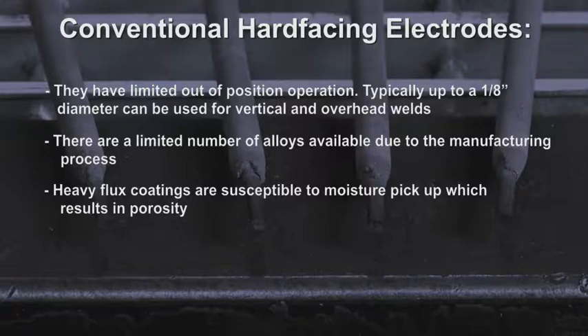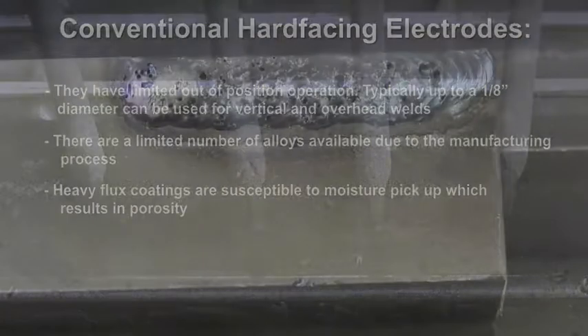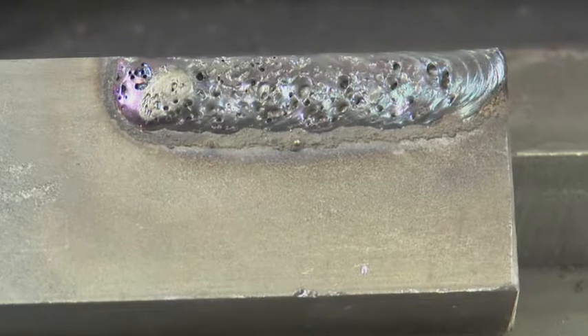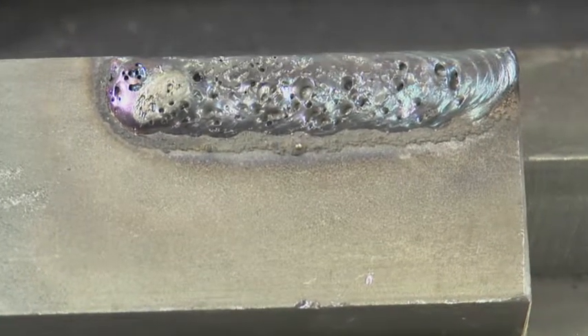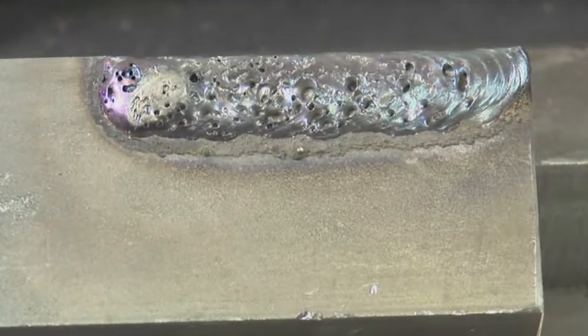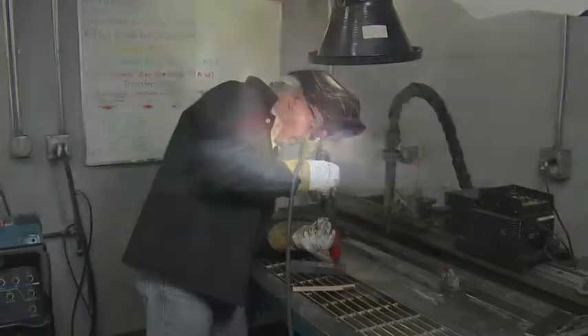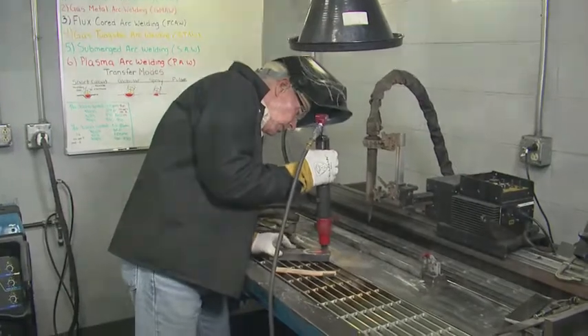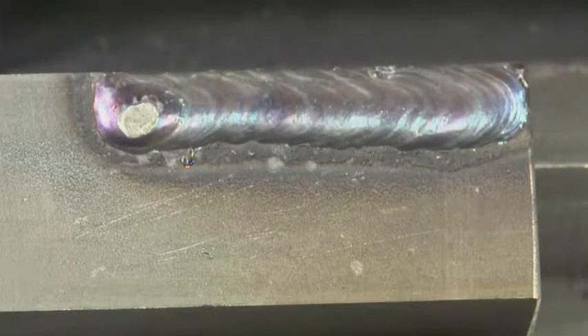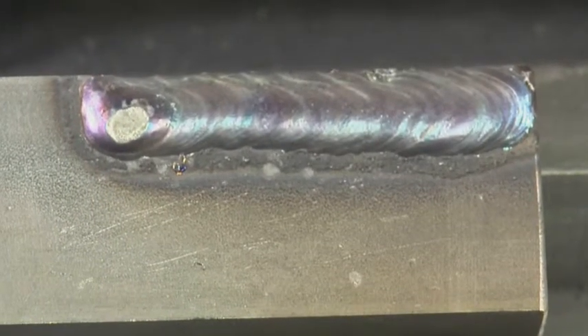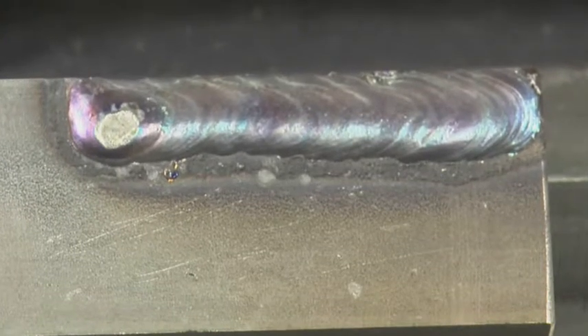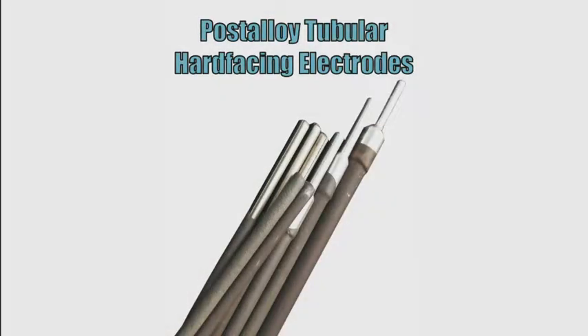Heavy flux coatings are susceptible to moisture pickup, which results in porosity. Have you ever had porosity in a weld due to moisture when using conventional flux-coated stick electrodes? Postalloy tubular electrodes with their moisture-resistant flux coating solve that problem. Note that there is no porosity, making them ideal for use in humid environments or outdoors. Now, onto tubular hard-facing rods.